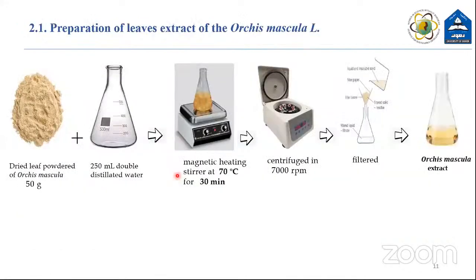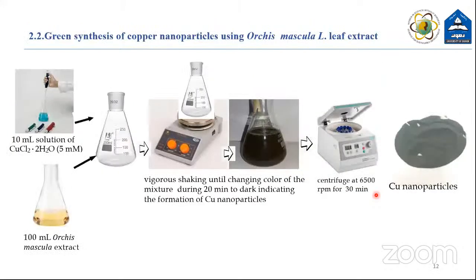Preparation of leaf extract of Orchis. For preparation of the leaf extract, 50 grams of dried leaf are mixed with double distilled water, then stirred for 30 minutes at 70 degrees centigrade, followed by centrifugation and filtration to obtain Orchis mascula plant extract for further use.